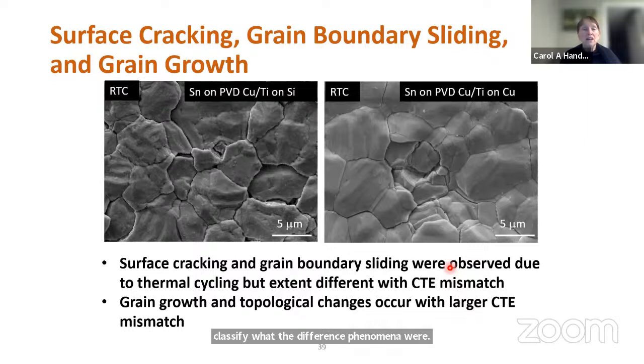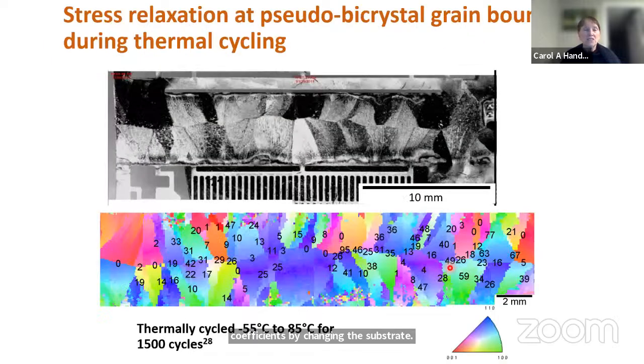Surface cracking, grain boundary sliding were observed due to thermal cycling, but the extent was different with CTE mismatch. So we changed the thermal expansion coefficients by changing the substrates, and we looked at these in lots of different ways. We also looked at pseudo bicrystal films to try to see what's happening along these grain boundaries. So again, this is a tin thin film, but formed by melting and solidification. So it's about 20 or 30 microns thick. We thermally cycled these from -55 to 85 degrees C for 1,500 cycles.